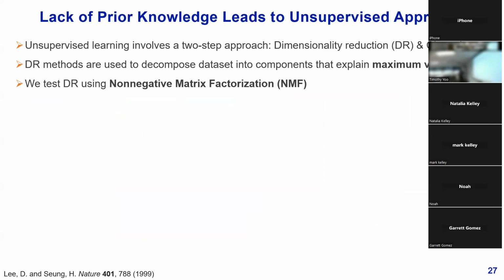And so that lack of prior knowledge correspondingly leads us to using an unsupervised machine learning approach. In this case, what unsupervised machine learning is going to do is apply a two-step approach of dimensionality reduction. What dimensionality reduction does is it generally decomposes your data set into a set of components or features that helps retain something called maximum variance. Essentially, it's features that are going to help distinguish one data point amongst the rest. And so in this case, we're going to be using something called non-negative matrix factorization.